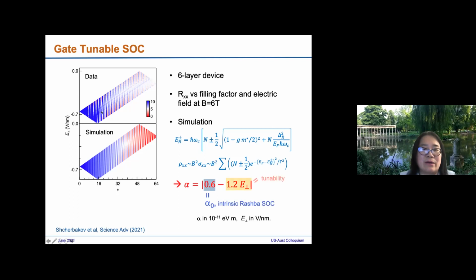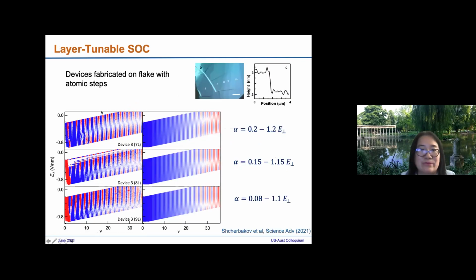We did this as a function of number of layers. Then we can also track how it changes as a function of number of layers. This is a device with 7, 8, and 9 layers on the same flake. So we can tune this Rashba spin-orbit coupling parameter by electric field, and also by the number of layers. It actually decreases a little bit going from 7 layers to 9 layers.